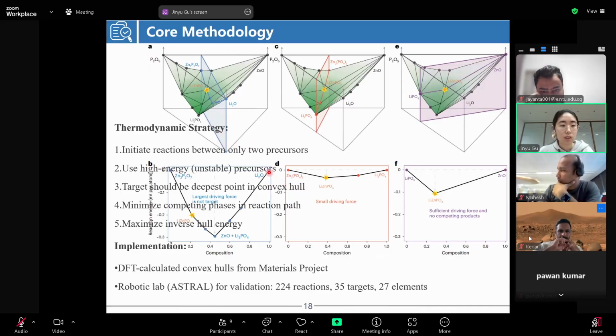They use thermodynamic strategies like initiating reactions between only two precursors, and using high energy or unstable precursors. This strategy is related to the fifth, maximize inverse hull energy. And then the target should be the deepest point in the convex hull. This is right, and this is not so good, and minimize the competing phases in reaction paths. So this is suitable for the thermodynamic strategy, and the convex hull was collected from Materials Project, and they use the robotic lab for validation.